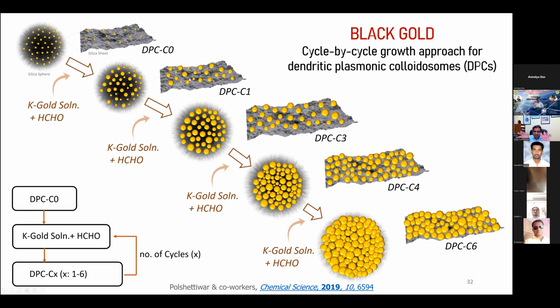As size increases, that reduces the gaps between the particles, and that's what we did. We ran several cycles because we didn't know what the best optimized gap was, so we tried to make a series of materials to find out the best gap to get broadband light absorption.